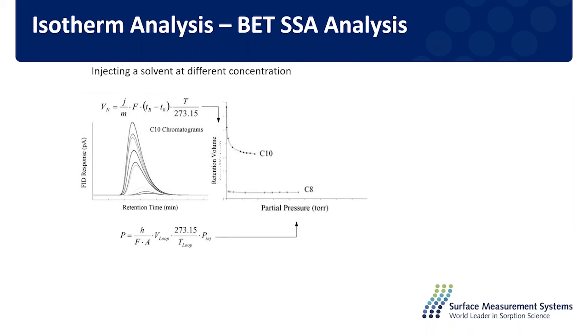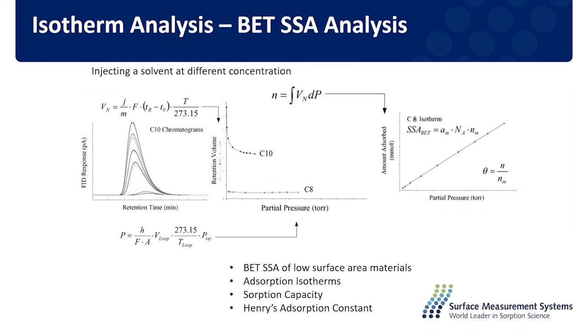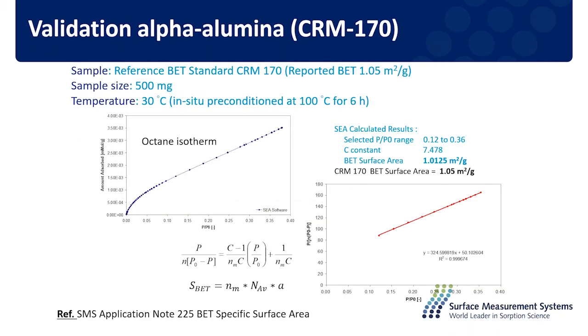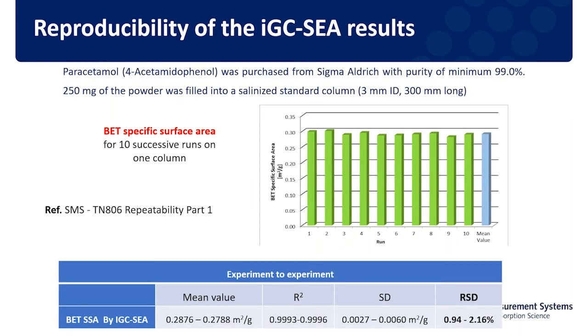Isotherm analysis in SEA is just how it's performed, step by step. We inject a series of concentrations, we get the partial pressure and retention volume, and then the adsorption curve. We validated our instrument using standard materials, and we got exactly the same surface area. We wrote an application note about it, so it's available online and on request. We also did a study where we used a commercially available paracetamol and measured its specific surface area, which is quite low, less than 0.3 square meters per gram. But you can see how accurately and nicely we could measure the surface area of this sample.